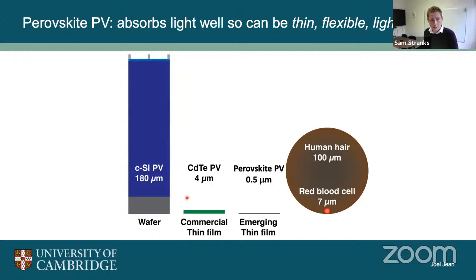But then when we go to some of the other thin film technologies, we see this one which is cadmium telluride, which is 4 micrometers. But when we go to perovskite, we only need 0.5 micrometers to absorb almost all of the incident sunlight, which is extremely thin. For reference here, this is a human hair, which is 100 microns, and a red blood cell, which is 7 microns. And this perovskite cell, you can see, is extremely thin, and that's enough to absorb the sunlight. And this means that we can make extremely thin and flexible and even lightweight solar cells, which I'll talk about in a few moments.